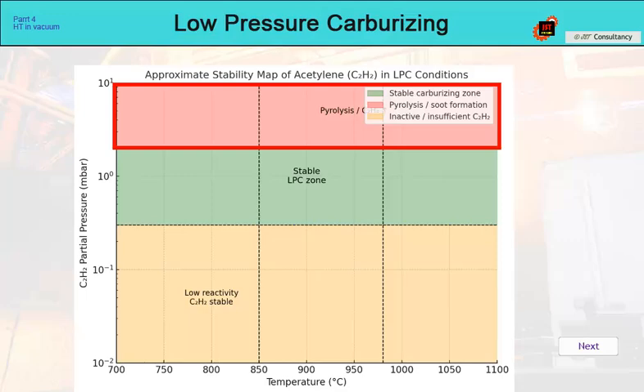soot formation occurs. A properly set low-pressure carburizing process has a short saturation period, a pressure of 0.5 to 2 millibars, a temperature greater than 900 degrees Celsius, and a correct gas flow without ethylene formation. For clarification, it is necessary to add that the accuracy of pressure regulation should be plus minus 0.05 mbar.